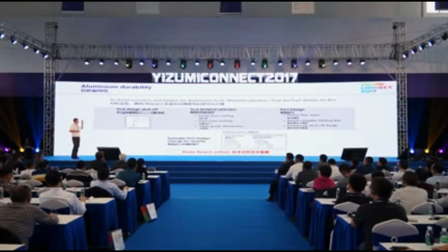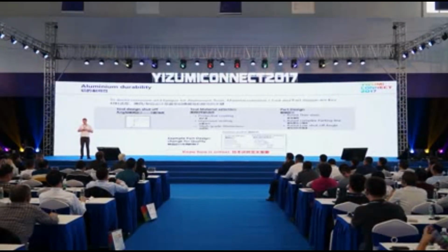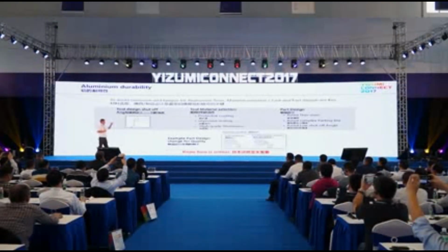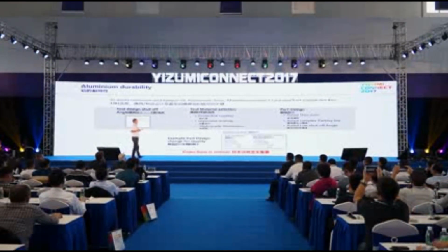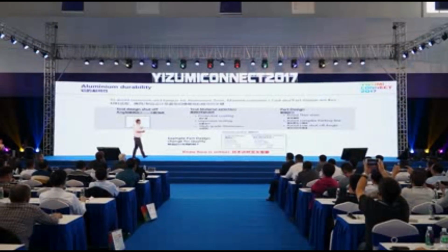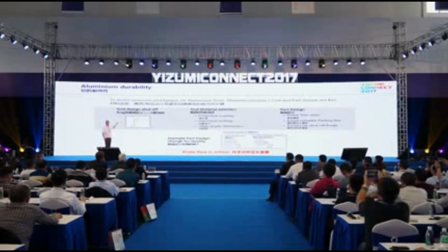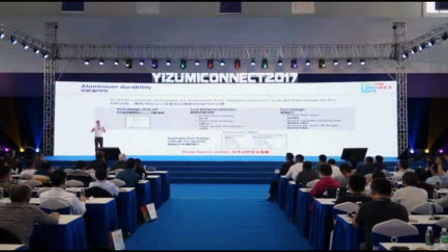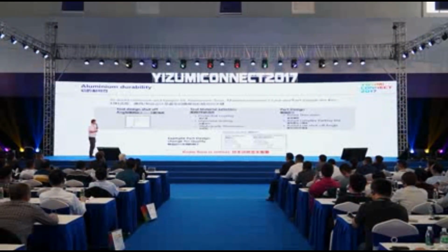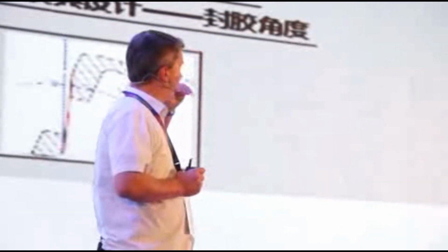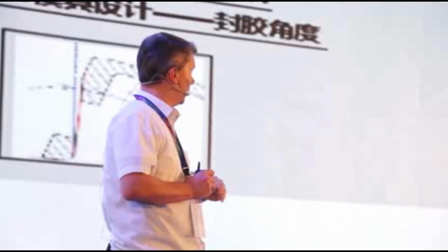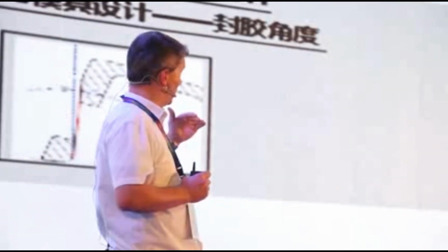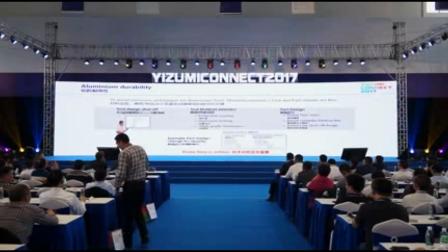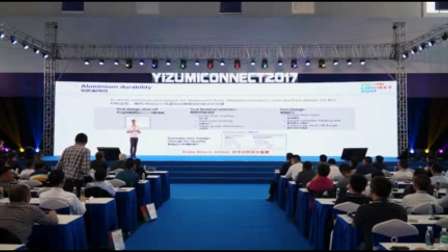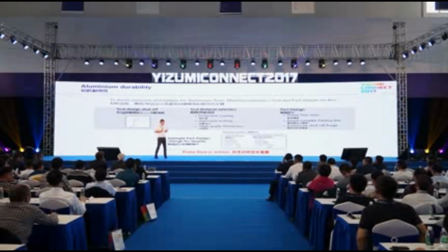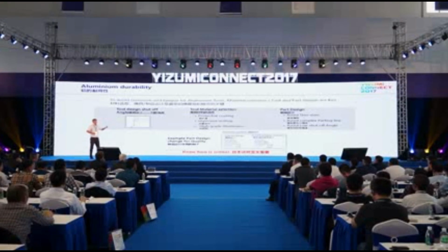So, to avoid corrosion and fatigue, which are really the two biggest problems with aluminium, material selection and tool and part design are key. For example, when designing your product, you don't want to have a very small shutoff angle. Aluminium rubbing together is not a good idea. It's not a good idea with steel. The tool material selection: we have protective coatings, we have improved venting, we have high grades of aluminium we are using to avoid these problems. And part design: you don't want to have thin steel, you don't want to have complex parting lines, and you want to avoid low shutoff angles. Know-how is critical for this.